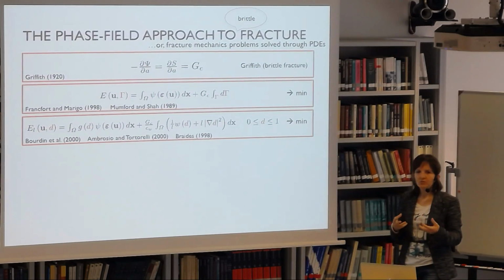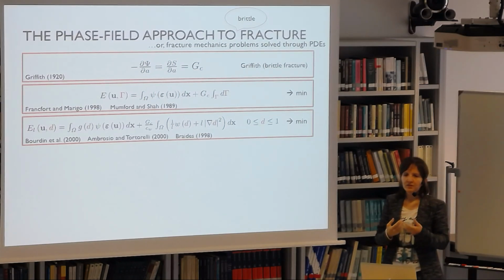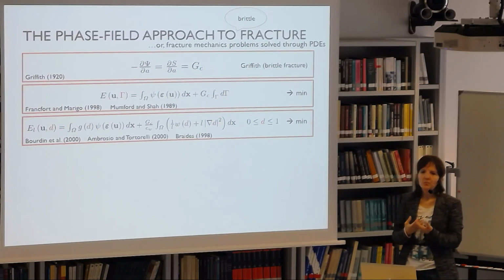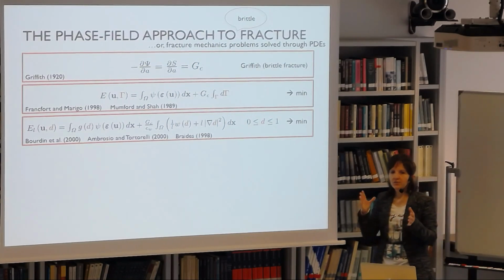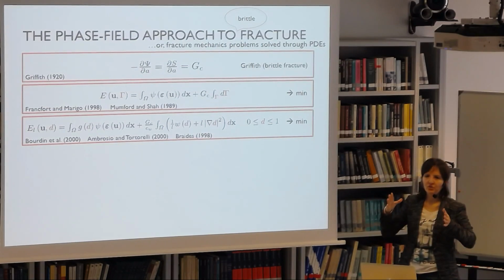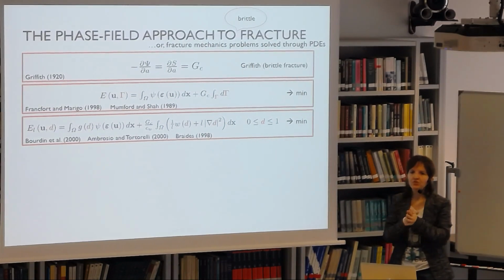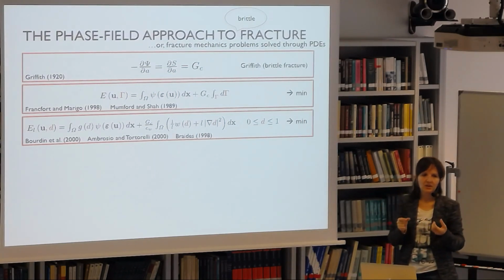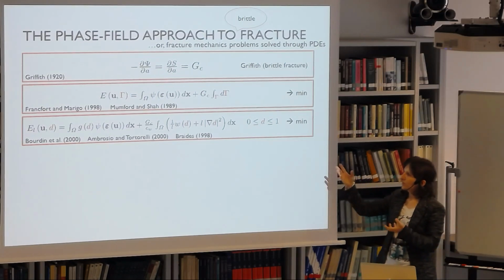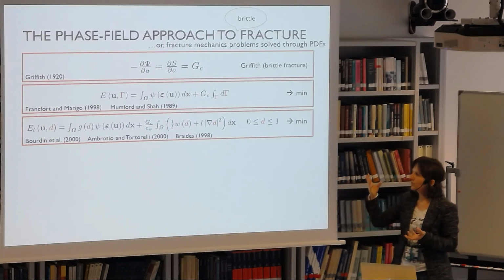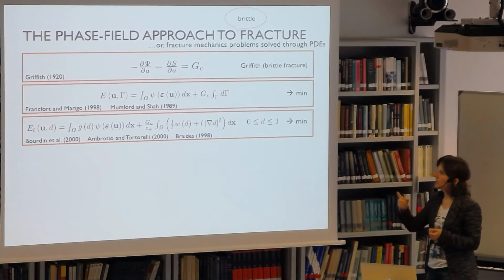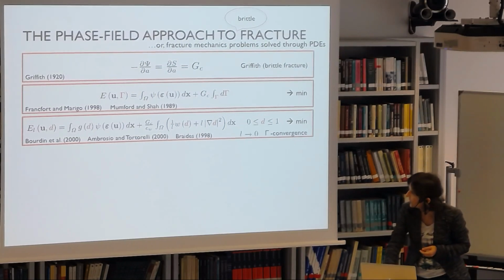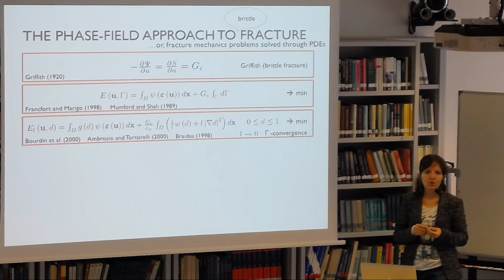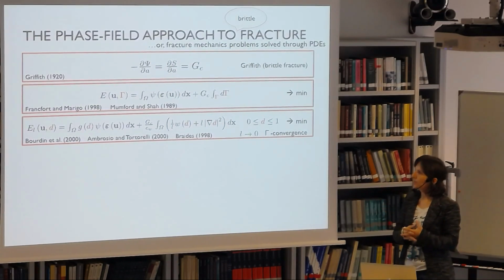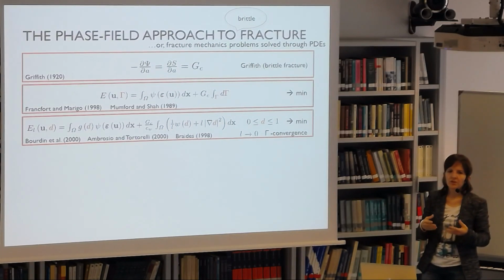And we all know most likely that without a gradient regularization, a local damage approach would be ill-posed. So there would be a mesh sensitivity where, as you refine the mesh, the dissipated energy due to damage decreases to 0. So if you have an infinitely fine mesh, you don't dissipate anything. This is because you have localization on a band of width one element in the finite element implementation. So as soon as you introduce a gradient, the gradient of d, then of course you have a length scale coming into the picture. This is indicated there as L. And L is a very important parameter in this model. There is a very important mathematical property that if L tends to 0, then you have the so-called gamma convergence property.